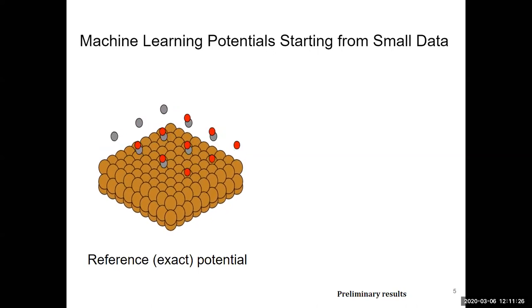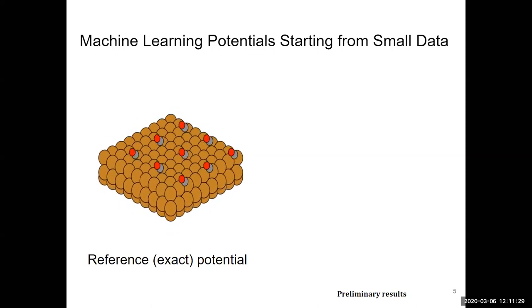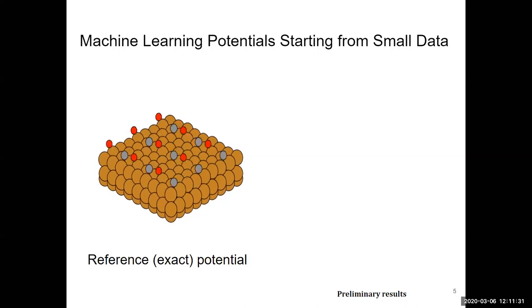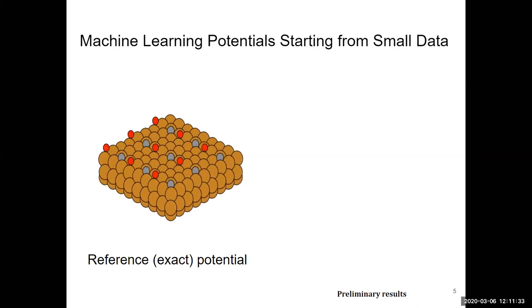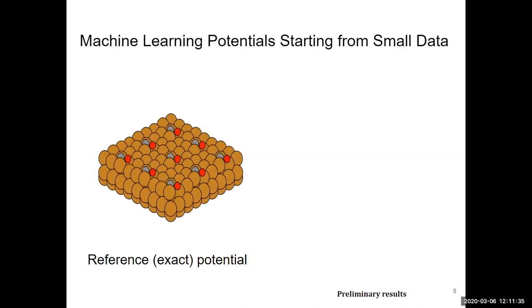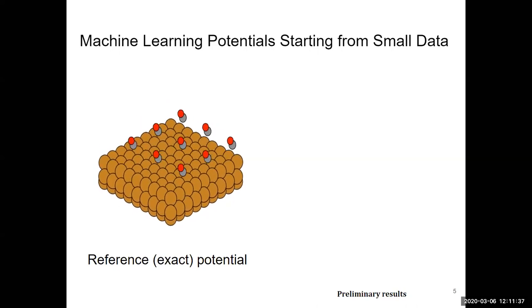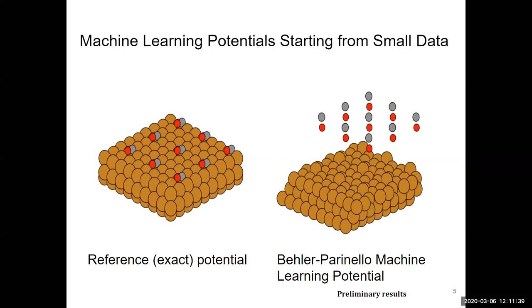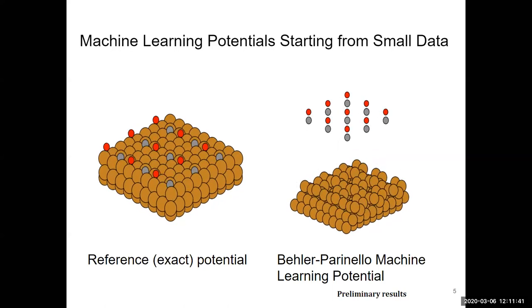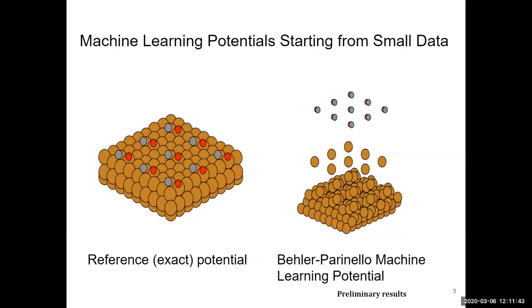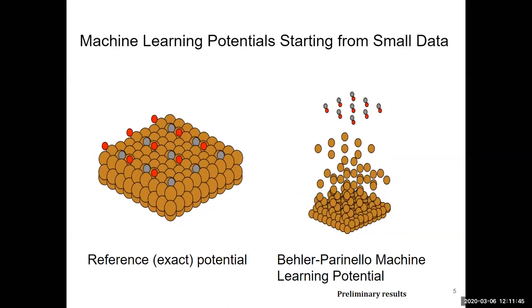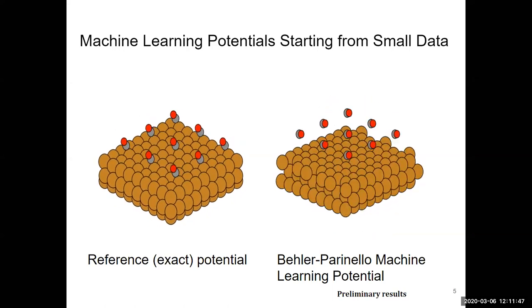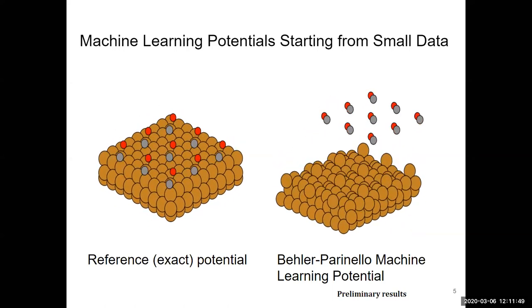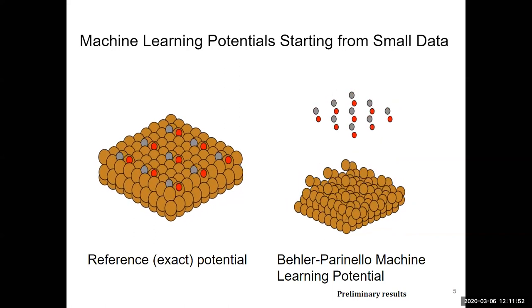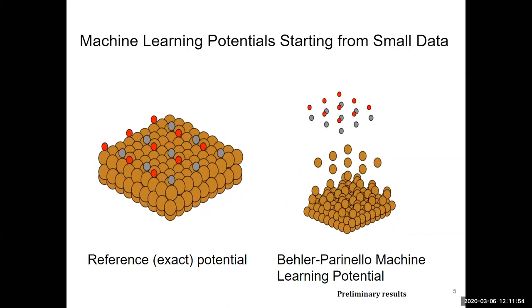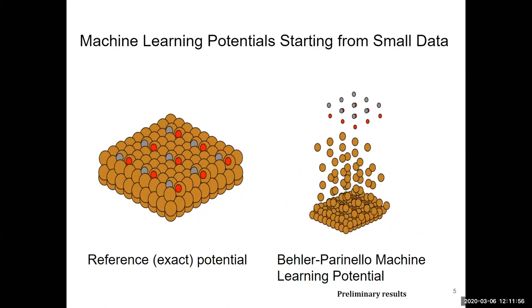And if I take the first 100 snapshots from this trajectory, and I train a machine learning force field, a standard Behler-Parrinello one, the mathematics of which has been around for 12 years now, nothing fancy, and then project forward, things go off the rails right away, right? There's nothing in the data set that says that the copper has to stay together. There's nothing that says that the coppers can't really overlap. The COs sort of fly off the surface and have this really crazy stretch frequency that is definitely unphysical.